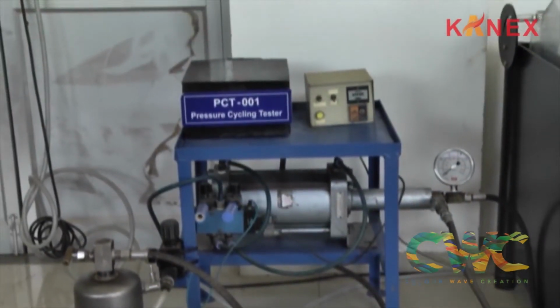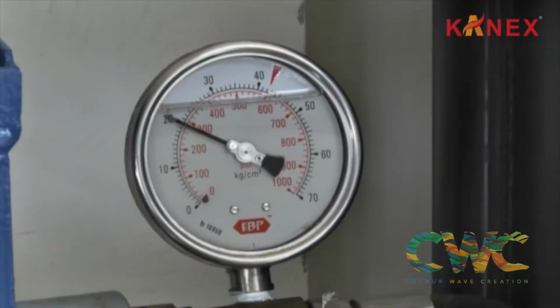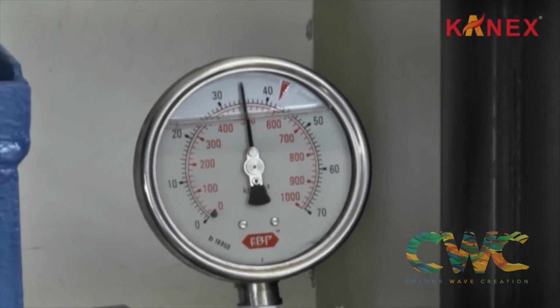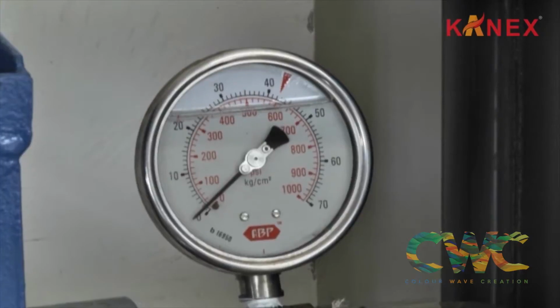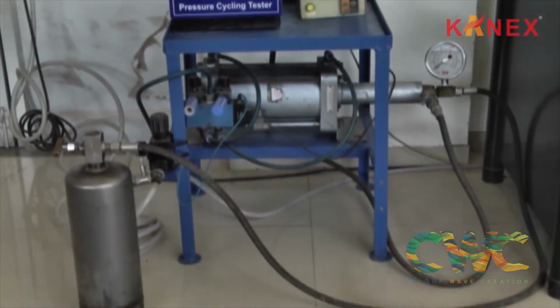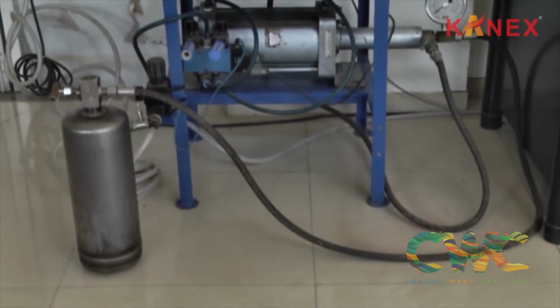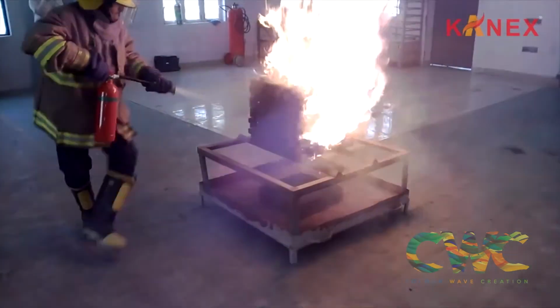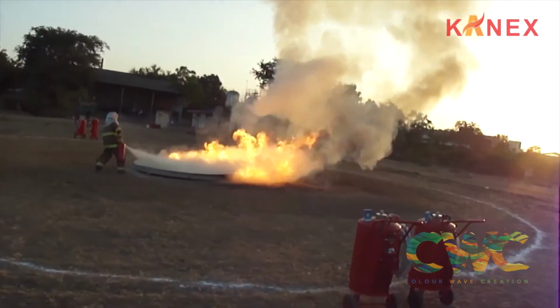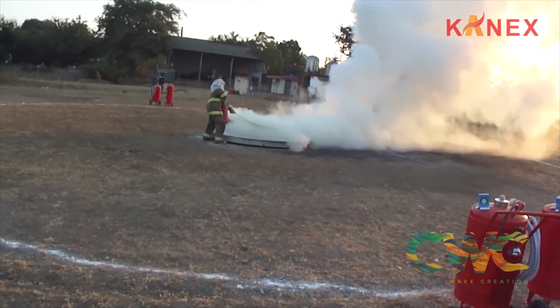Pressure cycling test. The cylinder shall be subjected to a pressure cycle of 500, that is from 0 to 35 bar and back to 0, at the rate of 6 cycles per minute. At the conclusion, the cylinder shall comply with the burst test. Fire rating tests. Fire performance tests are conducted in a well-established fire testing facility by trained firemen.